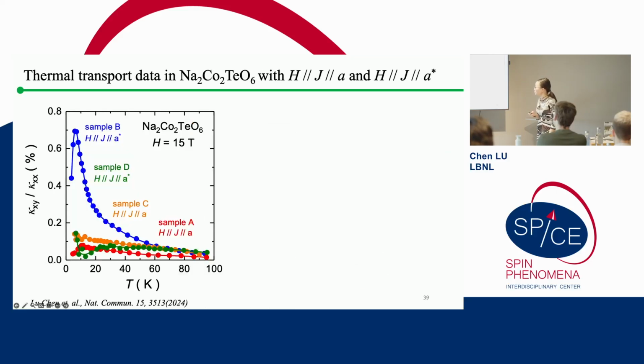At this point, when we saw this non-zero planar thermal Hall effect, we thought, okay, the global symmetry tells you shouldn't have it. So what happened? We needed to check if it can be reproduced or not. So what we did next is measure in another 2 sets of samples. In total, we measured the planar thermal Hall effect in 4 different samples. What I plotted here is the so-called thermal Hall angle versus temperature in these 4 different samples. You can see that they show a very strong sample dependence.